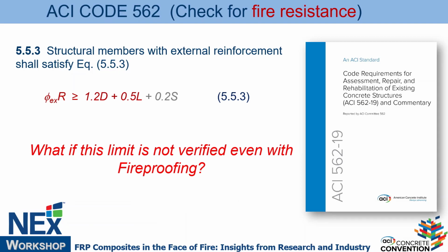Okay, so now, what if with all this fire protection, I cannot make it work? Well, maybe then FRP is not the right solution in this case, right? One thing I want everybody to keep in mind is ACI 440 has a limit on the strengthening, to keep FRP as what we call supplemental or secondary reinforcement. That means we're only increasing the capacity by plus or minus 40%, depending on the dead load to live load ratio. So most of the time we're not increasing the load significantly, and that's why most of the time if we have reserve in fire rating based on detailed calculation, it may be okay, and you don't need fire protection for the FRP. But sometimes you find you need it.